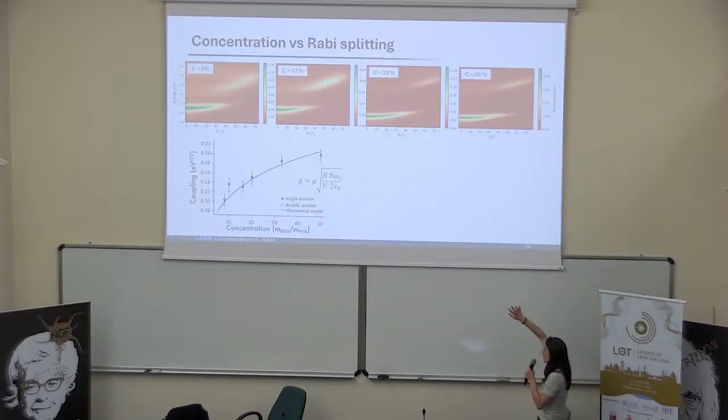But here, simply focusing on the concentration part, we start to see for a concentration doping of 8%, so 8% of dye over the polymer mass, the rising of the Rabi splitting at such low concentration, and this splitting increases rapidly for high concentration, up to 200 millielectronvolts. This is a very large number for a small molecule that is not a large aggregate.